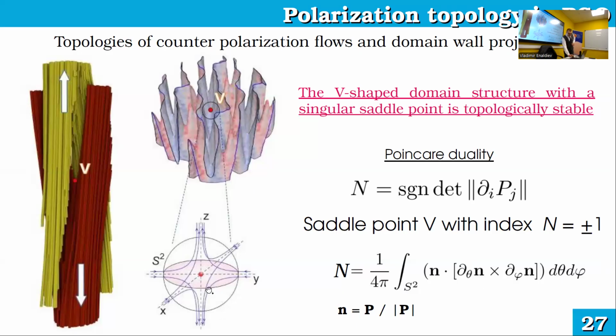Here you integrate the normalized vector of polarization over a small surface that surrounds this saddle point. And the values of this integral are exactly the same as the values of the index. So it's +1 or -1. Actually, this duality of description is formally called Poincaré duality. And exactly this connection between differential and topological properties gives you so-called topological stability, or topological protection. So this point is topologically stable.